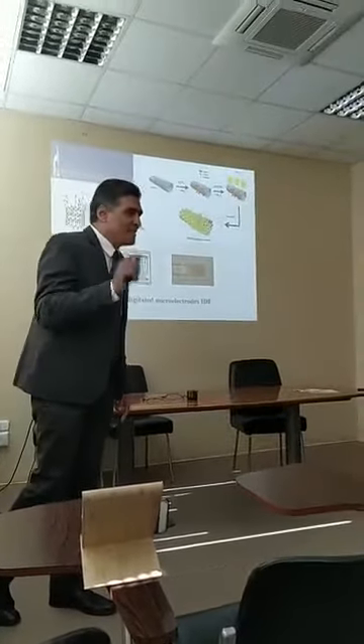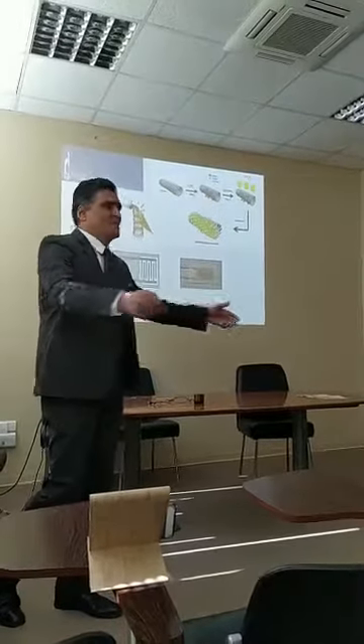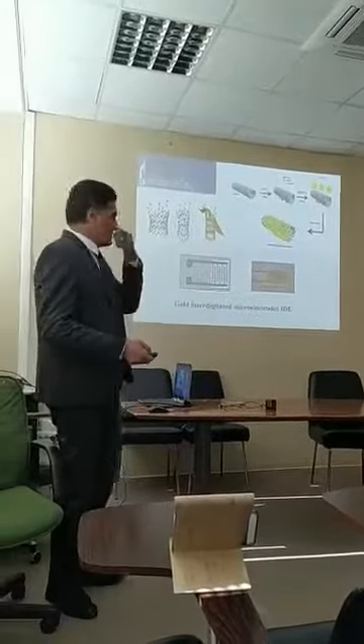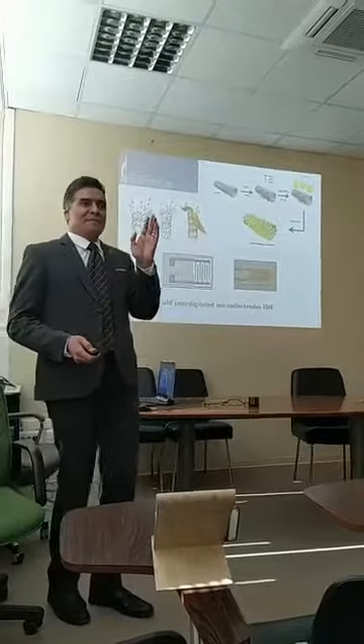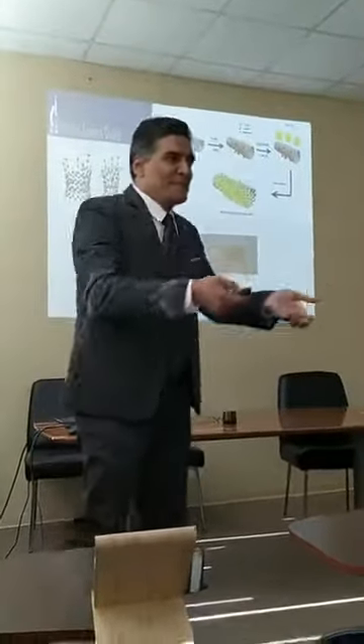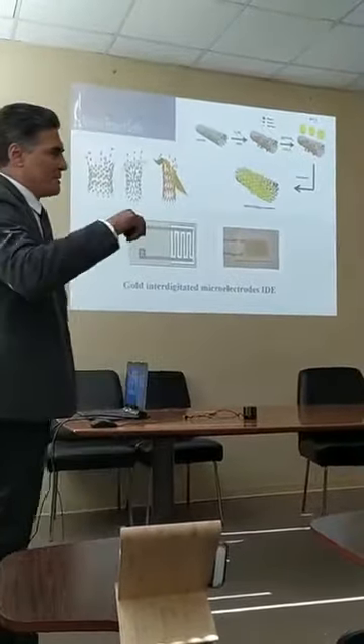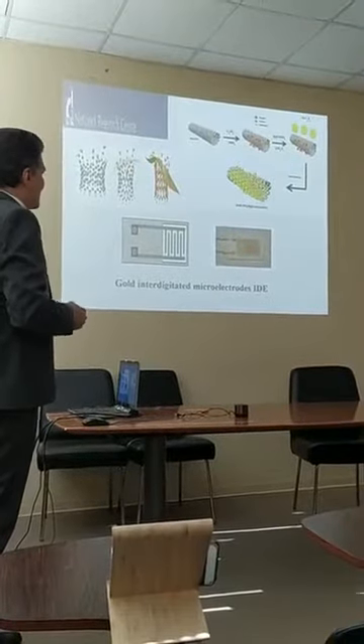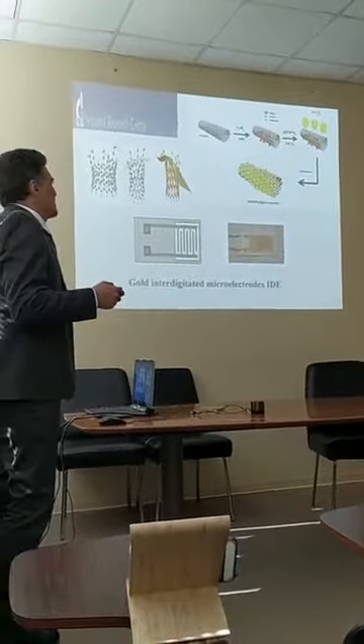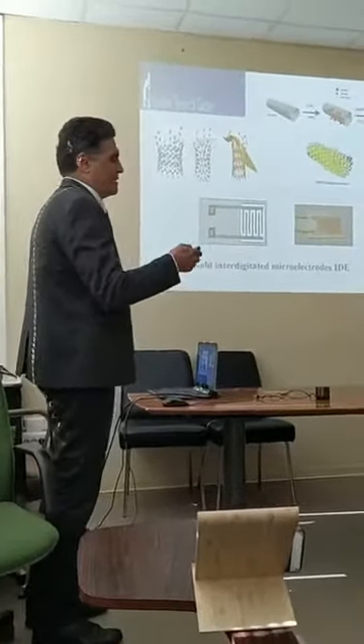So again, molecular modeling is the first step for the choice of selectivity, the choice of the combination of which metal oxide. You have different metal oxides. You have multi-wall carbon nanotubes, single wall carbon nanotubes, graphene oxide, and so on. You have different choices, which is very expensive. Then if you work with theoretical methods, you have different schemes. Just choose a few schemes to be treated experimentally. So you save money, and the disposal of these chemicals will be eliminated or reduced. In this sense, you can dedicate this class of computational work to be very effective in the work on volatile organic compounds or detection of harmful gases, not only in laboratories but also in industrial areas.